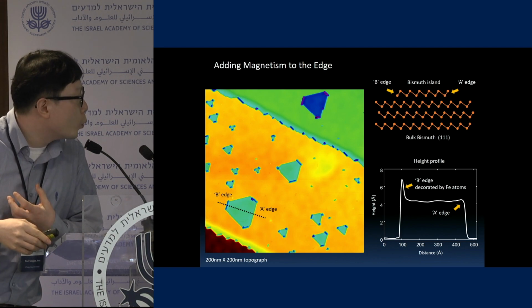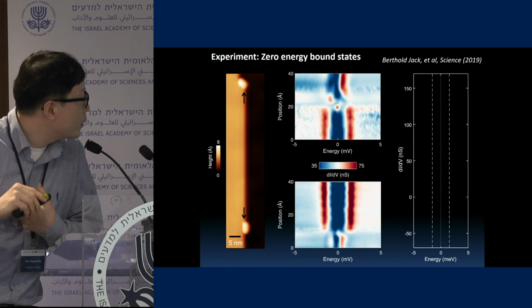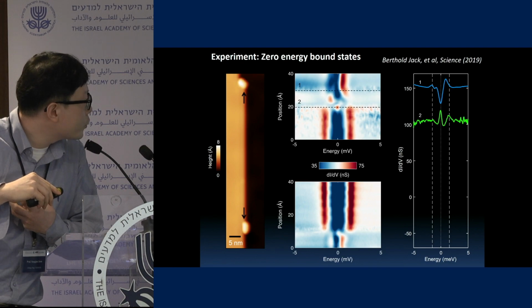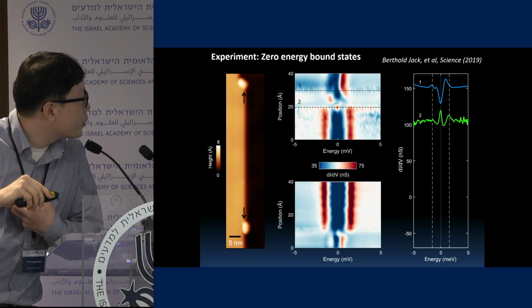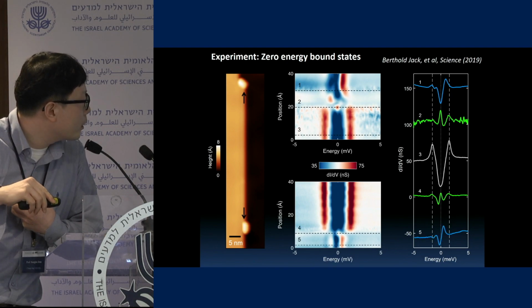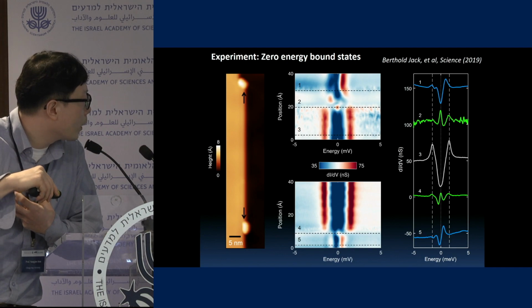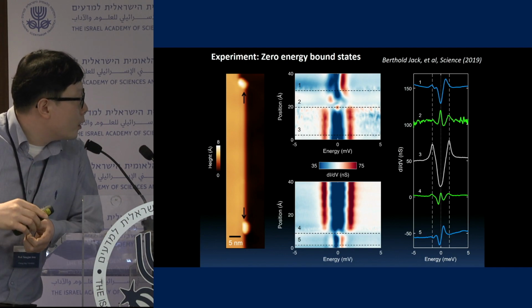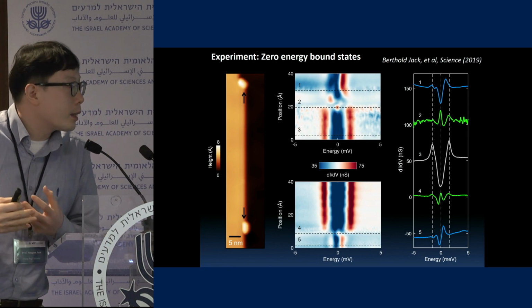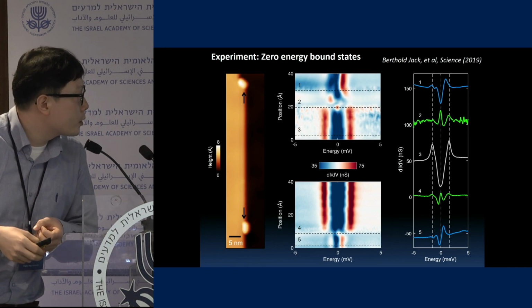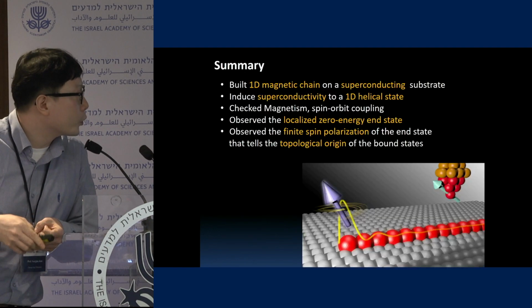And then we measure the spectrum here. This is the edge state. As you see here, as you go over these magnetic clusters, you see the zero-energy state is located only at the interface here. And the lower part is again the same, so you see the zero-energy state located at the interface here. So this is how we understand the theoretical proposals and realize them in real materials.